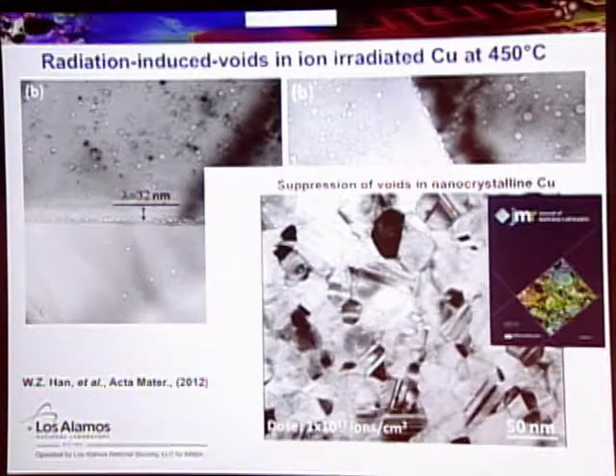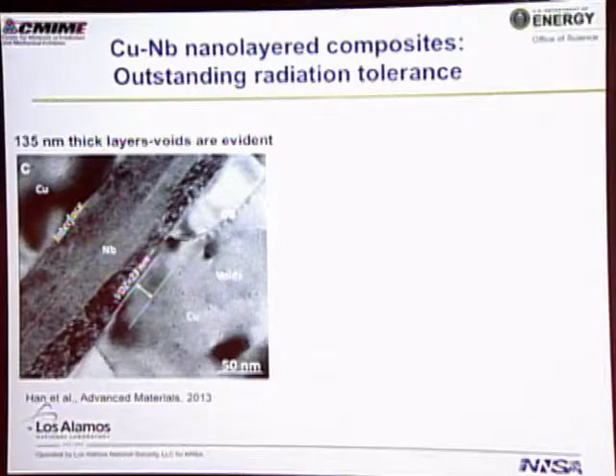If we drop the grain size down to nanocrystalline grains, what we can find is that, sure, you don't get as many voids anymore, but you still have these voids at the boundaries. This is some work published by another one of our postdocs, made the cover of Journal of Materials Research. So what happens if you layer the material? Now, if we start with 135 nanometer thick layers, what you find is that there are no voids right along the copper niobium boundaries. There are voids within the copper grains that make up the material.